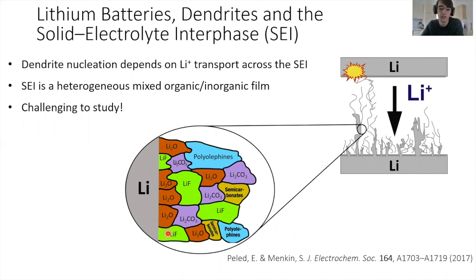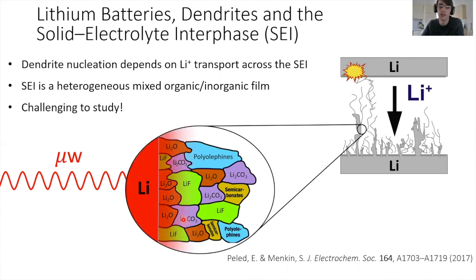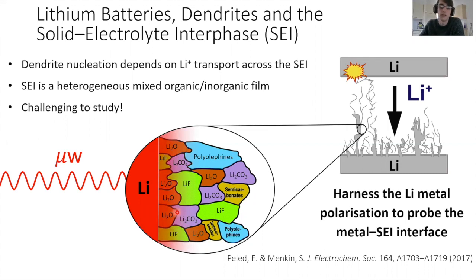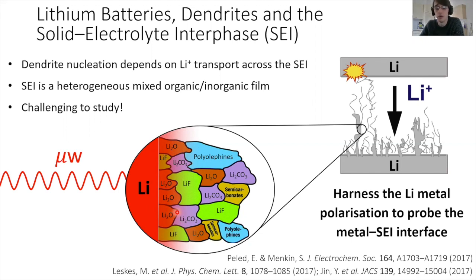And so you can see what we're going to do. We're going to irradiate with microwaves, hyperpolarize our lithium, and then we're going to transfer that into the SEI. This is very different to previous DNP experiments that have been performed on the SEI, where external biradicals were added. In these experiments, you have surface selectivity to the outside of the SEI, but you can't selectively observe this interface, and that's really what we're doing differently here.